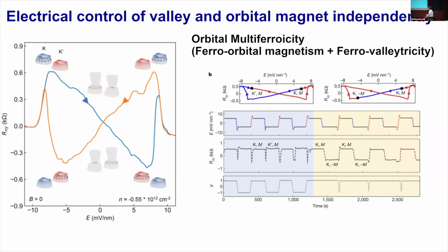And experimentally, we did observe this when we train the sample when the temperature is high. We apply a magnetic field, we field cool it. We train the sample, so it's likely to kill the domains at that stage already. And if we just do random cool down without magnetic field training, we don't have butterfly hysteresis like this. It's much more complicated. And that is the signature we believe there are small domains if you don't train properly.